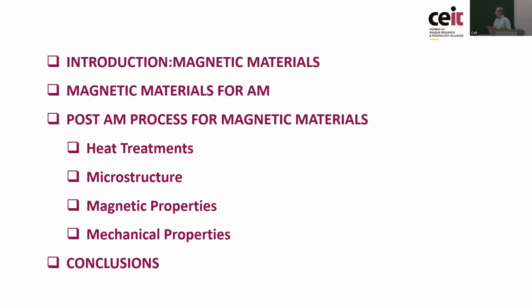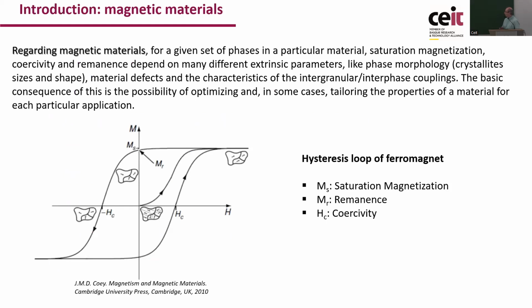First, we belong to the materials department, and our activity in this project has focused on the selection and developing of the materials. In particular, the problems in this project were related with magnetic materials. In the case of magnetic materials, the characteristic behavior is that when we apply an external magnetic field, H, they respond generating a strong internal magnetic field, which is the magnetization, which amplifies and adds to this external field. The material response is characterized by this kind of curve, which is a hysteresis loop.